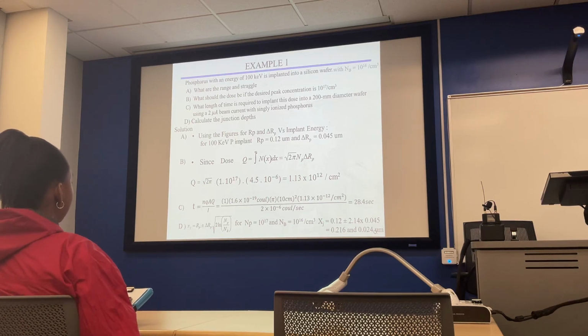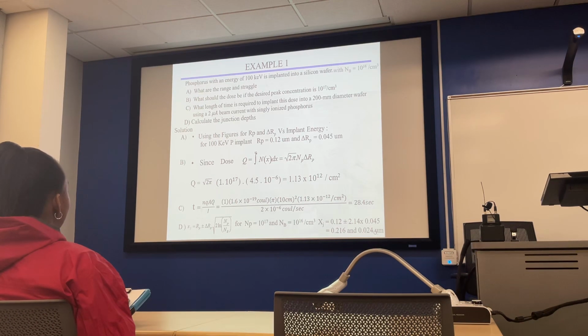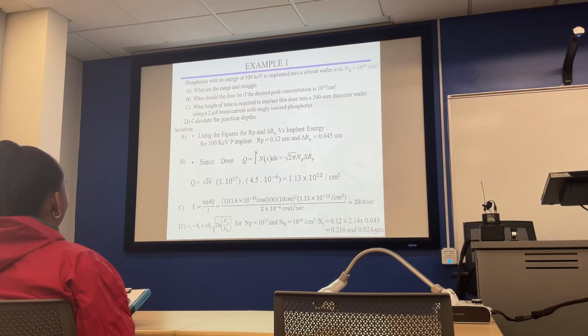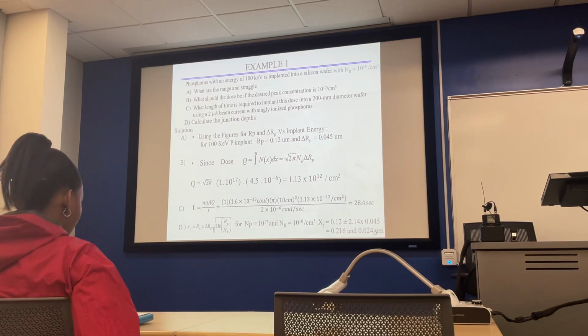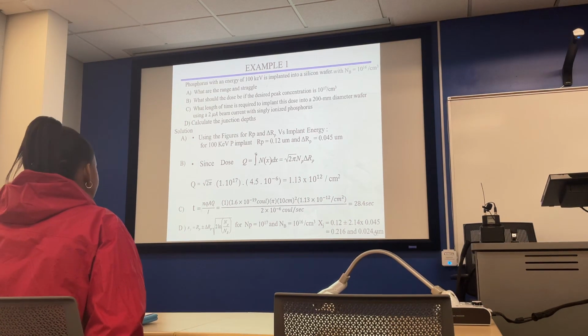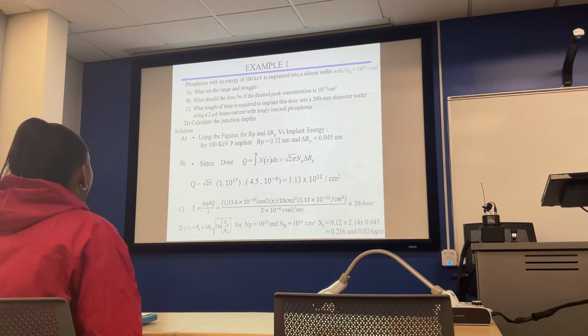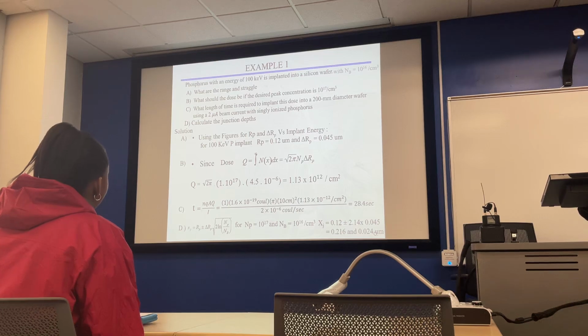Sometimes, and I'll talk about it later, you may want a doubly charged ion, especially in the case of boron, and we will discuss that. So don't always think that it is a singly charged ion, because there are some doubly charged ions, and for that all I have to do is remember to adjust the magnetic field, because what you collect out of that magnetic analyzer magnet is the charge to mass ratio, right?